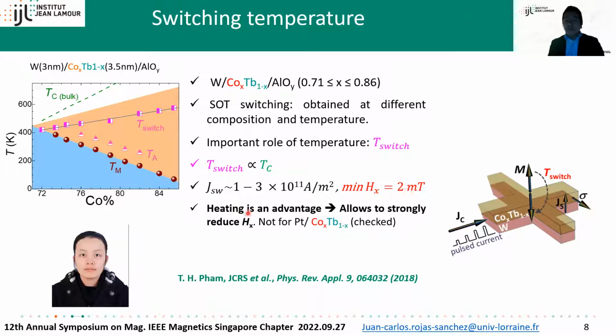So here heating plays a key role, but it's an advantage because it allows us to strongly reduce the perpendicular anisotropy. That means we reduce the in-plane field. That is not the case, for example, in platinum cobalt terbium. We have not published that, but we have checked it.